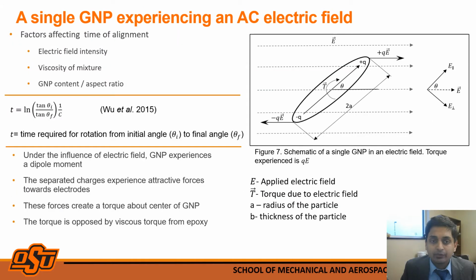To figure out the amount of time required for alignment, it is important to understand what exactly happens to a graphene nanoplatelet when it's experiencing an electric field E. When it's experiencing an alternating electric field, the graphene nanoplatelet develops a dipole moment and charge separation happens, plus Q and minus Q, along the extremities of the particle. These particles tend to be attracted towards the electric field in this direction. These forces create a torque around the center of the particle, and it causes the particle to rotate.